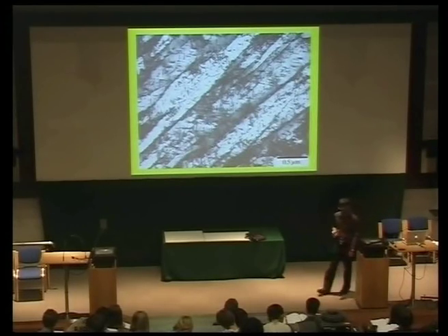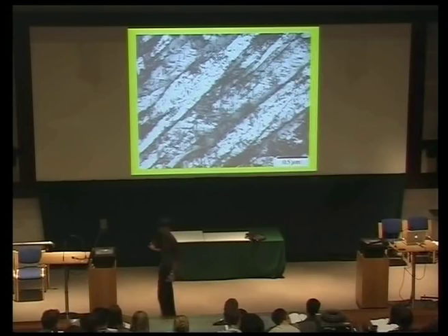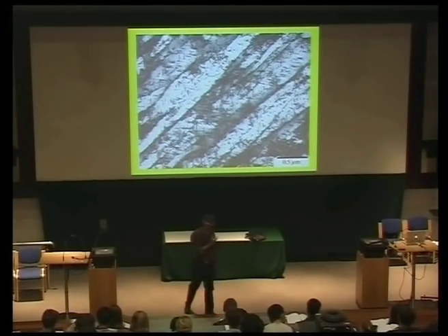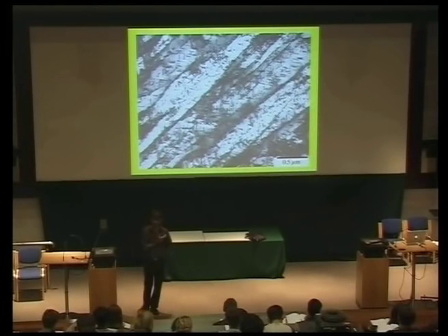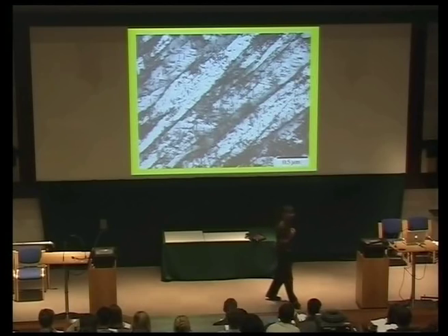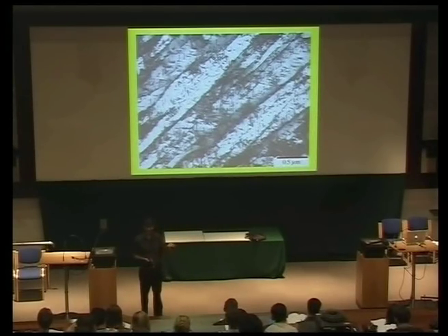And this is a transmission electron micrograph showing you a huge array of precipitates put into the steel. And these precipitates would be very stable. We have already discussed this. How can I make these precipitates extremely stable? When we were talking about the tempering of martensite, what do you think these precipitates might be? Remember, it's going to operate at 600 degrees centigrade. So if we produce these by tempering martensite at 200 degrees centigrade, that's no good. So what kind of precipitates might these be? Alloy carbides. So for example, molybdenum carbides, chromium carbides, and a whole variety of very stable carbide phases generated by tempering at a very high temperature of maybe 500 or 600 degrees centigrade. So these are the secondary hardening steels that we discussed earlier.